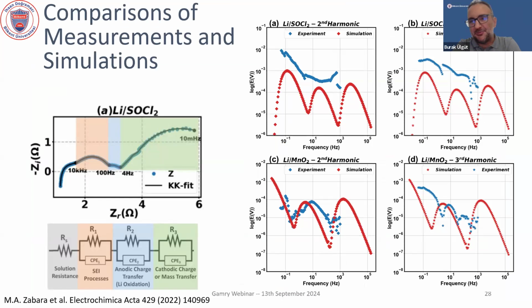Are we taking our own advice? Of course. You can see in the lithium manganese oxide case, when we plot the second harmonic, I'm talking about the bottom graphs here, the simulation is just the simulation of the initial transient, and you can see the nonlinearity we are seeing from the experiment pretty well matches the simulation. Now, there are differences because we are simulating with a capacitor and the battery exhibits a CPE. So that's really the difference between the two. And I didn't want to force my student to work out the Kirchhoff's laws for a constant phase element. So that's why I left it this way.